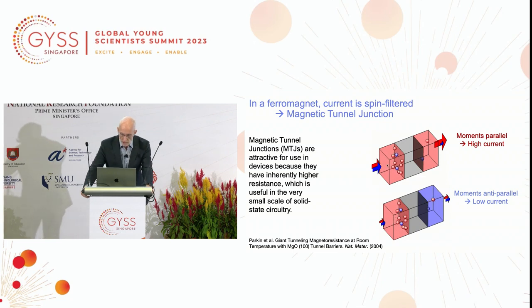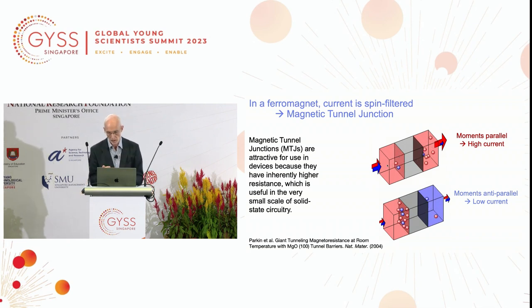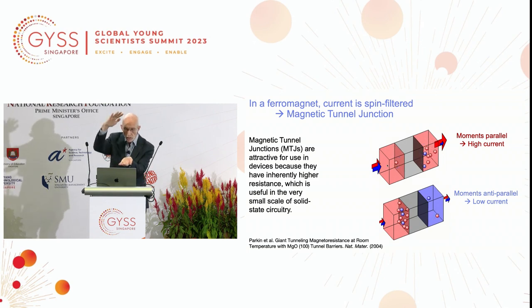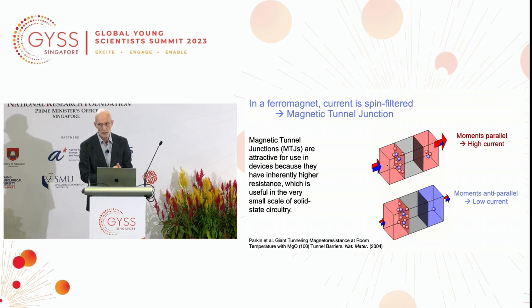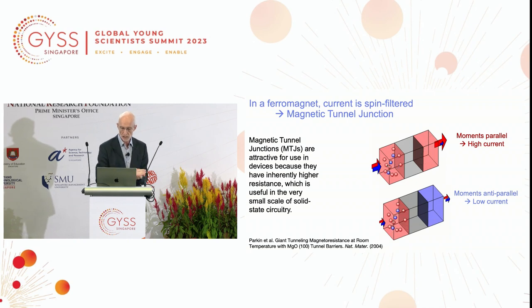Now the advantage of this system is that the resistance can be much higher for current perpendicular to the layers than in a metallic structure. In a metallic structure a few atomic layers thick, as in the spin valve, there's virtually no resistance in the perpendicular direction. This system has high resistance. Moreover, it has high tunneling magnetoresistance.